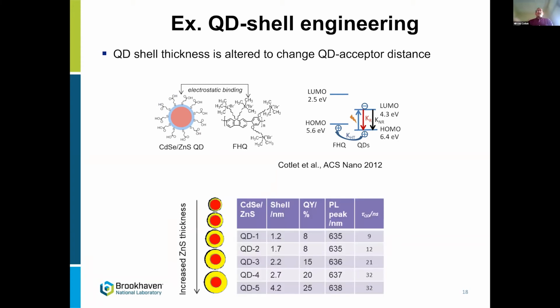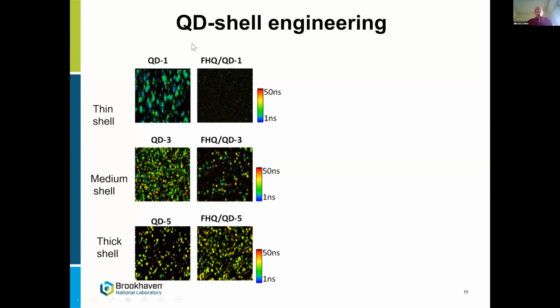As a result, we can control how fast or how slow the hole moves from the quantum dot into the polymer. So we created a series of quantum dots with the same core size and different shell thicknesses. We can see that the quantum yield of the quantum dot increases with the increase of the shell thickness. That's just the effect of the passivation. But when we look at the transient emission images, the quantum dots alone on a non-interacting surface like glass do show emission depending on the shell thickness. When we combine them with the polymer, which is a hole acceptor, we see complete quenching for a very thin shell, some quenching for an intermediate shell, and no quenching for a thick shell.